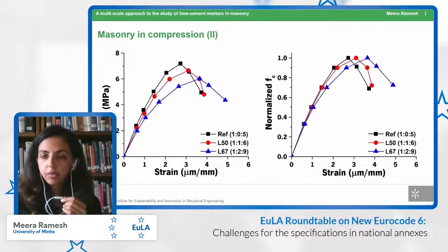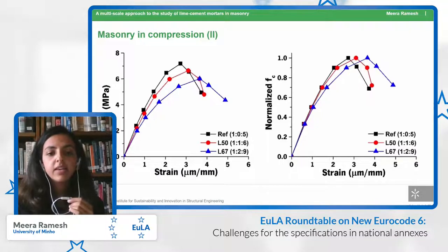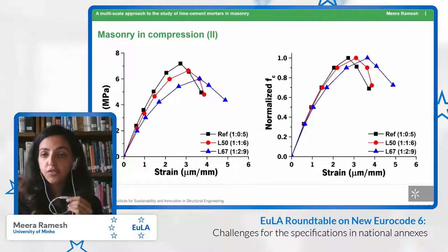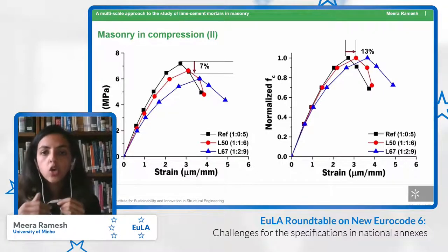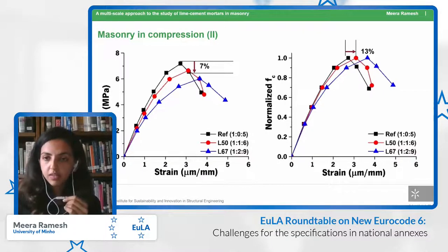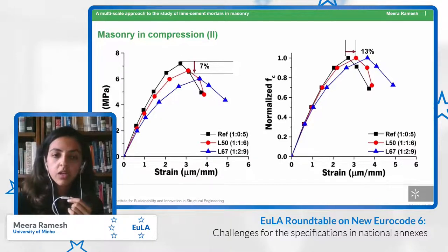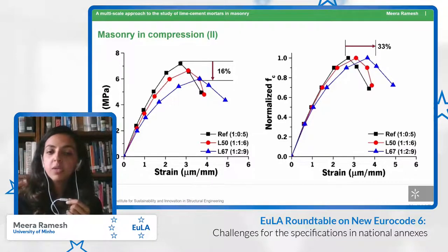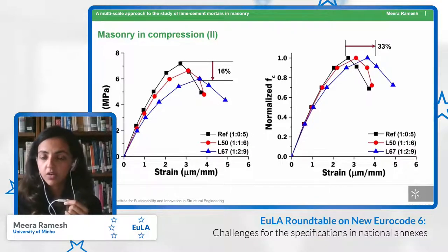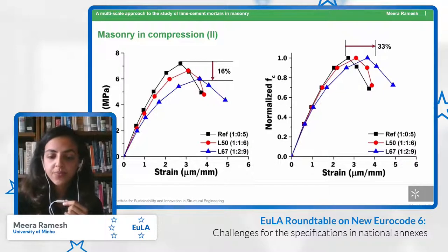To discuss this a little bit more in detail, what you see on your screen right now is L67 is blue in color, L50 is red, and the reference mix is black in color. So we found that between the reference mix and L50, there was a 7% drop in strength, but 13% greater strain capacity. Similarly, between the reference mix and L67, there was a 16% drop in strength, but a 33% greater strain capacity.